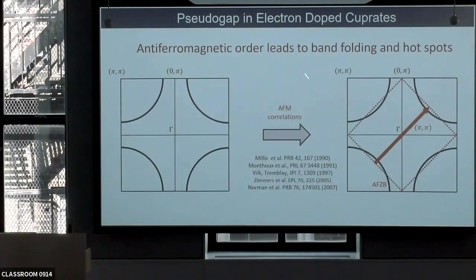So here is the simplest picture of the Fermi surface of the cuprate, one large hole-like Fermi surface centered around the pi, so the corner of the zone. And in a situation where antiferromagnetism is well established, you now have a reduced Brillouin zone electronically, and so this particular direction represents a plane about which the surface can be folded. So this is a so-called pi folding, and here when the two cross, that's where you have the hot spots with increased scattering and so on. In the electron-doped cuprates, this is seen experimentally quite well in terms of a suppression of spectral weight over here.